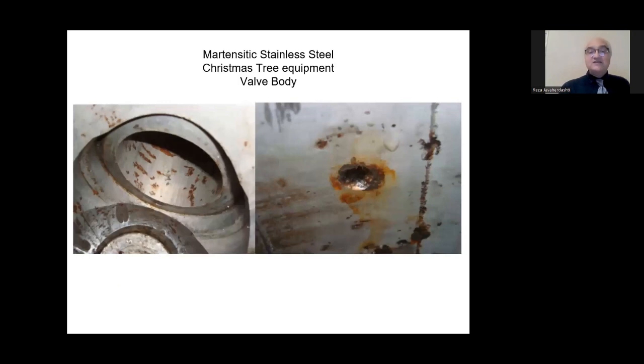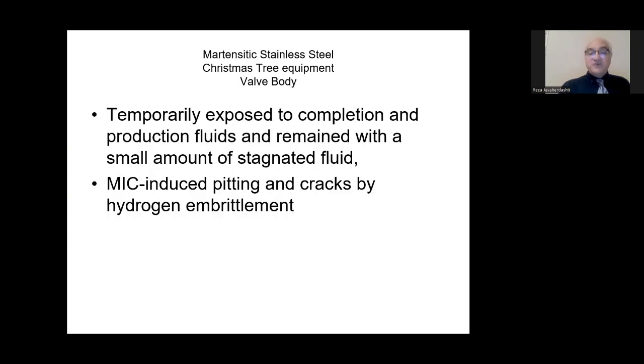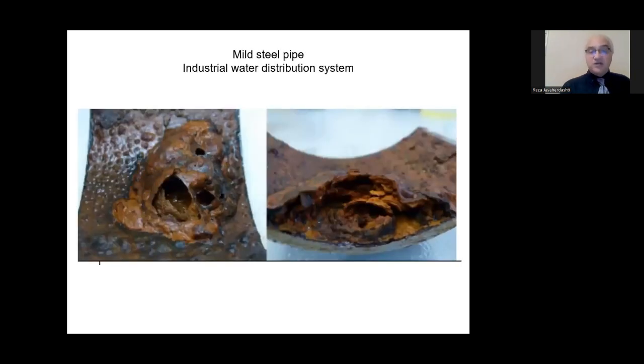Then we have this case for corrosion in Christmas tree equipment. The valve body was temporarily exposed to completion and production fluids and remained with a small amount of stagnant fluid. Therefore, when you have this stagnant fluid, which has a lot of positive contributing parameters that would increase the likelihood of MIC, it is quite likely that you will get such morphologies. MIC-induced pitting and cracks by hydrogen embrittlement also occurred.